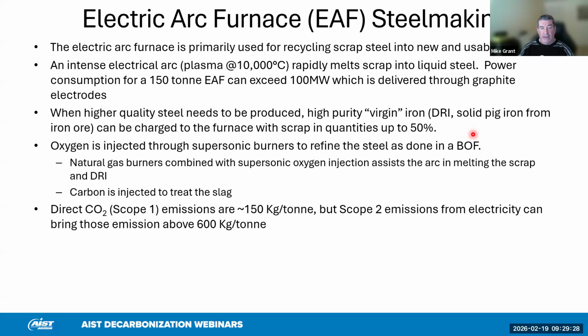When we need higher quality steel, we dilute the impurities. Scrap has a lot of impurities. We dilute those impurities with so-called virgin pig iron, which is DRI, or sometimes solid pig iron from the blast furnace. This is pure iron, charged to dilute the impurities from scrap, and it can be charged in quantities up to 50%. Oxygen is injected into the bath, just like in the BOF. But we also use oxy-fuel natural gas burners to heat the cold spots in the electric arc furnace. These burners also inject supersonic oxygen into the steel itself to assist in melting the scrap and the DRI. We inject a little bit of carbon. This is used to treat the slag, to produce what we call a foamy slag. It's a slag treatment process.